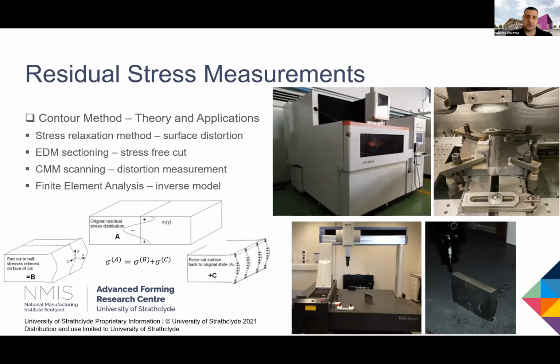But back to the residual stress measurements. As I said, the contour method is one of our go-to methods. Basically, we are taking the part and sectioning it with EDM simply because it offers the advantage of a stress-free cut. Then whatever stresses were locked inside that part are released, and that is experienced as a distortion in the cut face. We measure that distortion with a CMM.